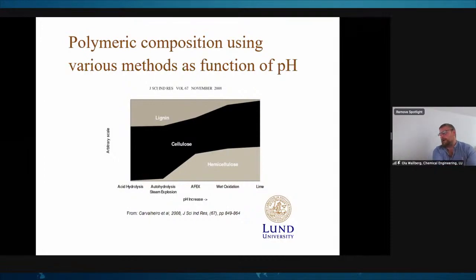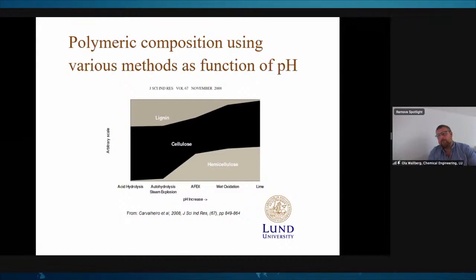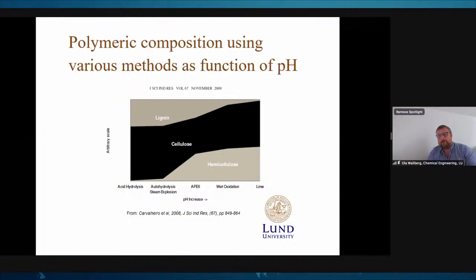When we talk about lignin fractionation, the most common methods are based on acidity or alkalinity — we work on a pH scale. This also has its origin from a biorefinery ethanol perspective. What it basically tells us is that if we work at low pHs, we typically dissolve the hemicellulose, and if we work at high pHs, we typically dissolve the lignin. Cellulose has a tendency to go unaltered through these processes.